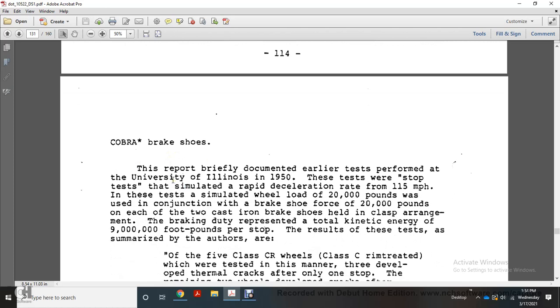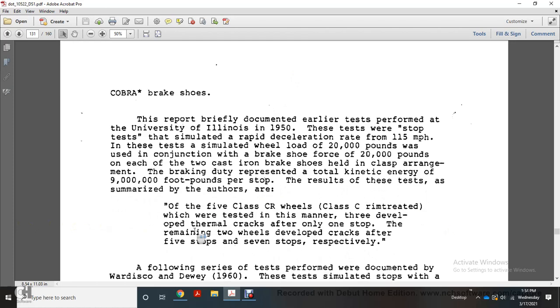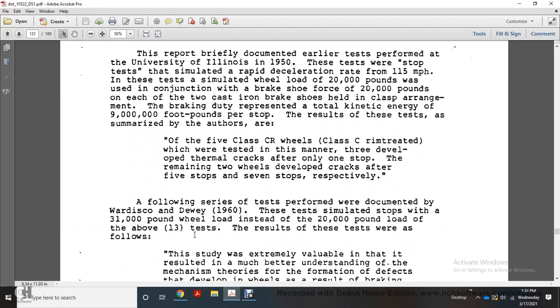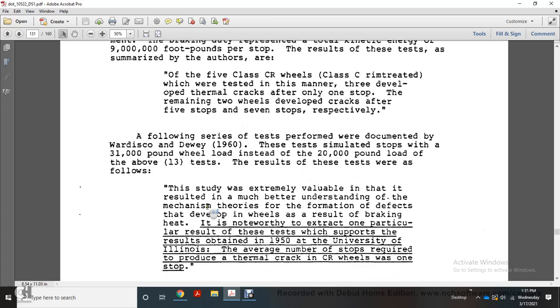In the University of Illinois' 1950 test, stop tests that simulated a rapid deceleration rate from 115 miles an hour. A wheel load of 20,000 pounds was used in conjunction with a brake shoe force of 20,000 pounds on each of two cast iron brake shoes held in clasp arrangement. The braking duty was representative of a total kinetic energy of 9 million foot-pounds per stop. The results of these tests, as summarized by the authors, were that of 5 Class C wheels, Class C rim treated, which were tested in this manner, 3 developed thermal cracks after only one stop. The remaining 2 wheels developed cracks after 5 stops and 7 stops, respectively.